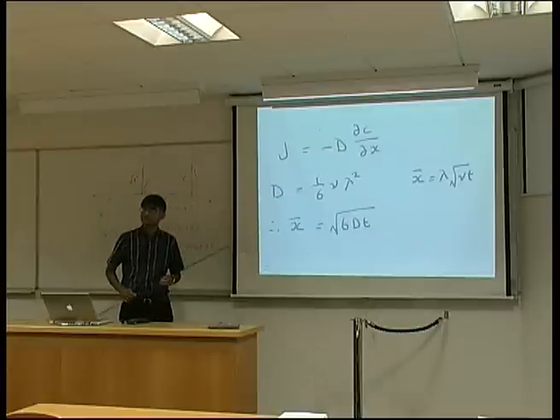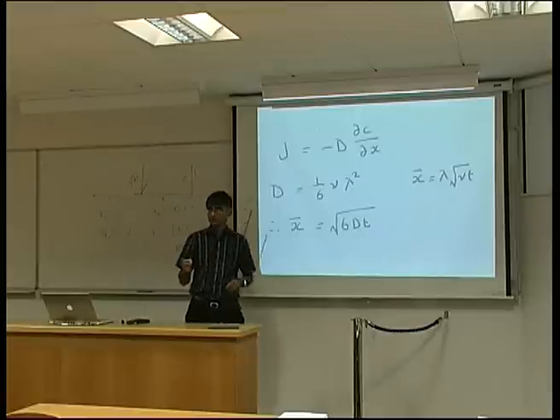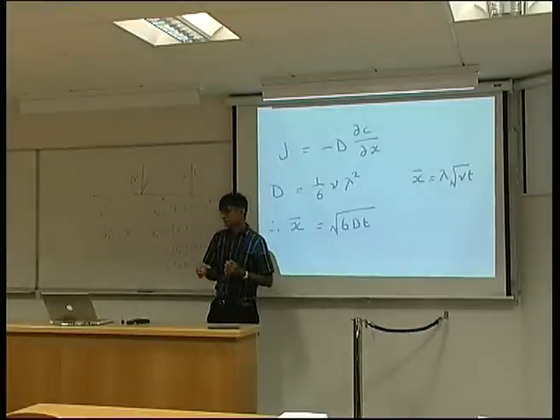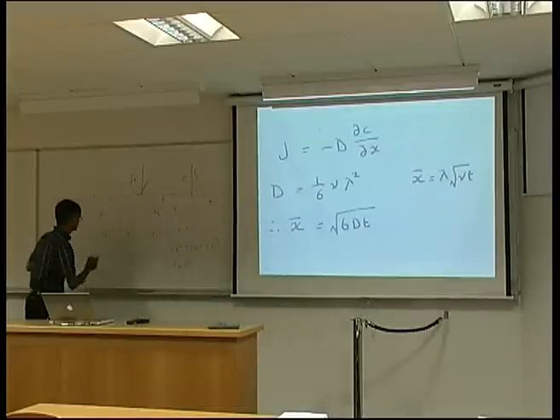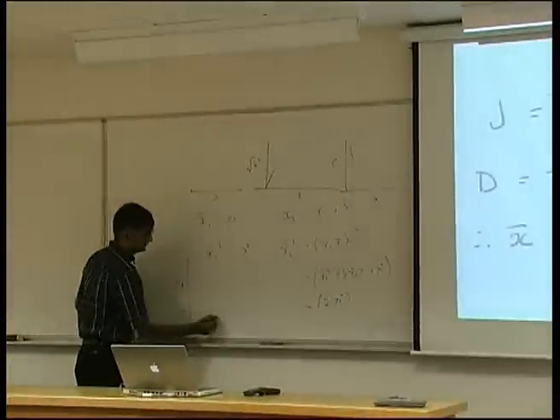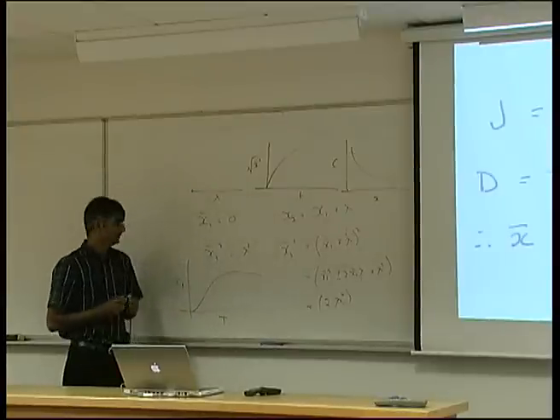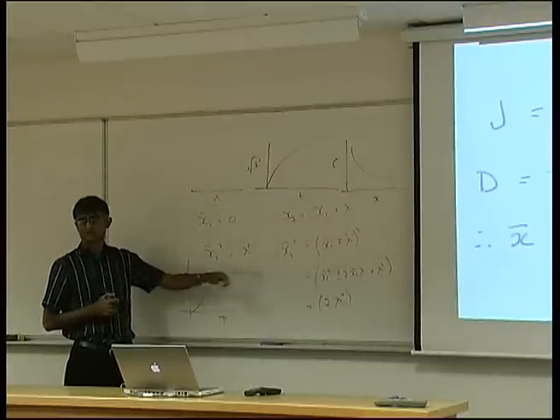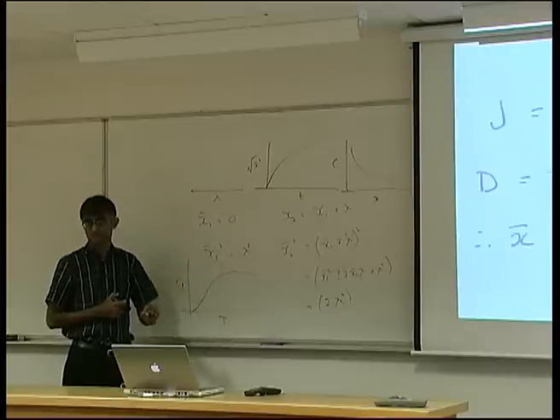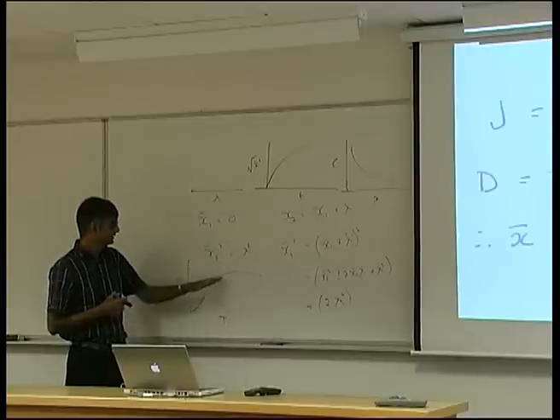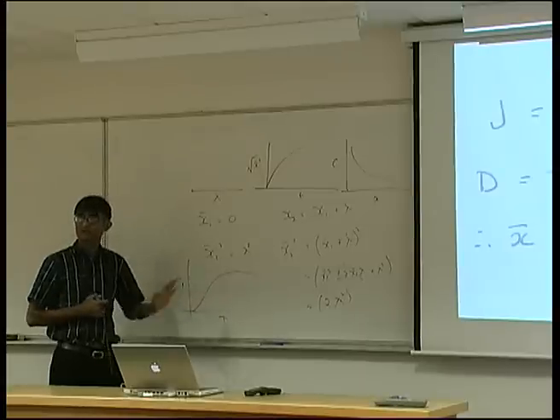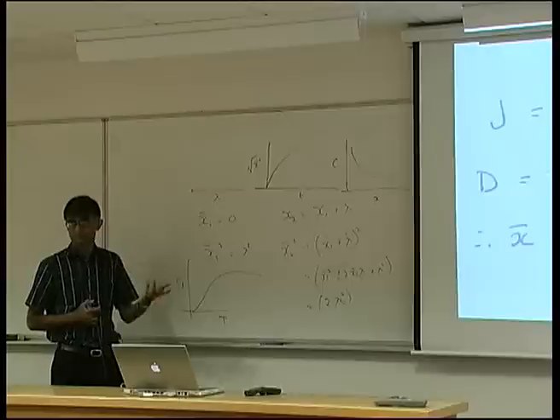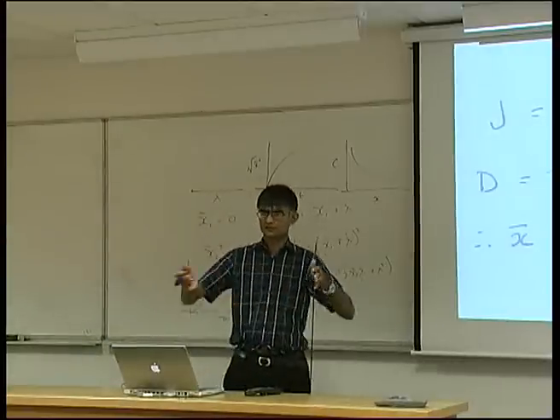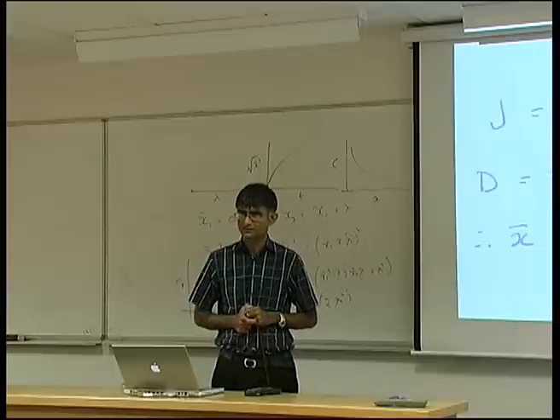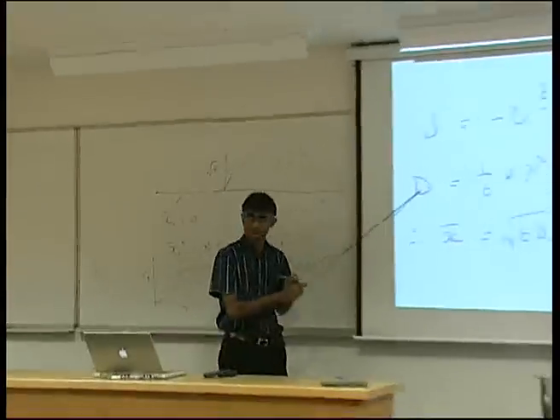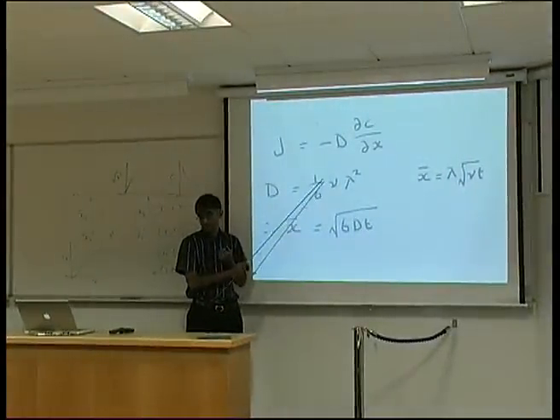How do you really determine the frequency? You mean fundamentally determine it or measure it? So fundamentally, when we plotted that heat capacity curve in the lecture on thermodynamics, Cp versus T, it had this form, did it? Yeah. And if we are in this regime, then things are vibrating approximately 10 to the power of 13 times per second. That's called the Debye frequency. When we get to here, things change. And you have to have the right theory to produce this curve to determine that frequency. You're considering lots of things oscillating in a coordinated manner, so it gets a bit complicated. But you will see how we actually derive the diffusion coefficient, because there is a lot more detail here than I have actually presented.